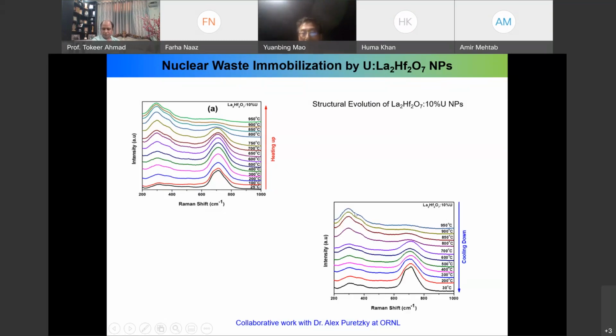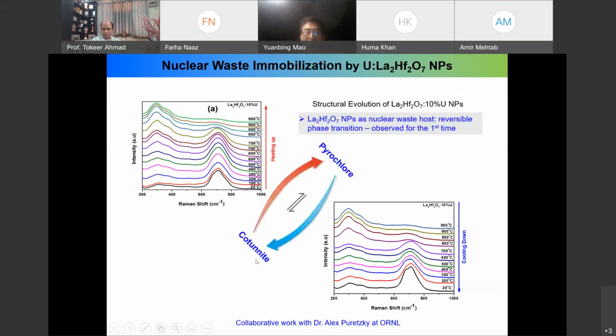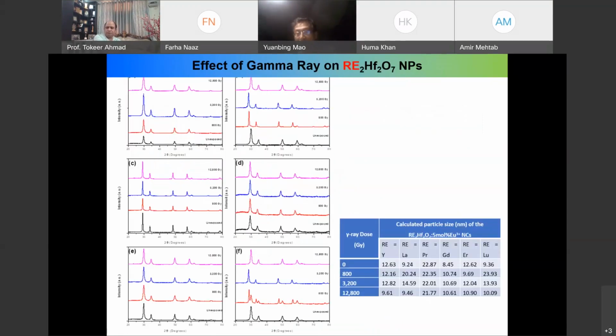And then we cool it down, and at a certain temperature, we take the Raman spectrum again. The interesting thing is once it reaches room temperature and we compare this spectrum here, it's the same as this one. So if I show you schematically, at room temperature it has a fluorite structure, and when it reaches 950, it has a pyrochlore structure. The important thing, this shows the heating up, this shows the cooling down. So this can be recycled. That means this nanoparticle hafnate has very good thermal stability and is also recyclable. That's related to the thermal stability.